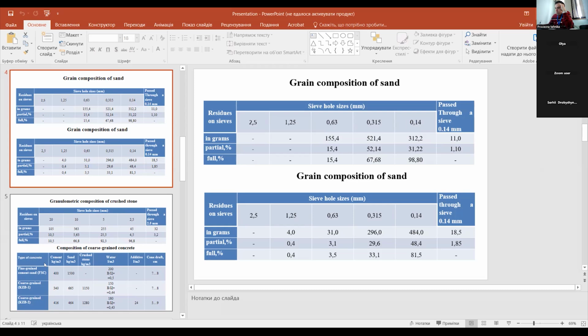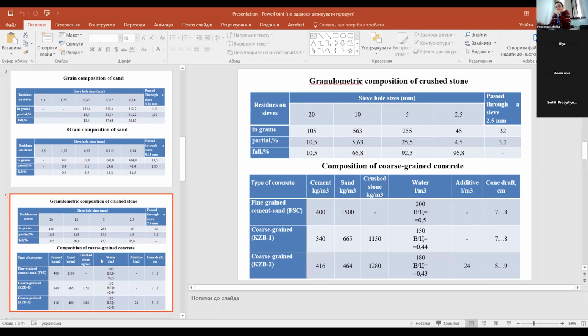The grain compositions of the sand for the fine-grained and coarse-grained concrete samples of the first type are presented in the table. For coarse-grained concrete samples of the second type, the fine aggregate was also quartz sand with characteristics determined in accordance with local standards. The fineness modulus of the sand was 1.18 and its grain composition is shown in table 2. Concrete mixtures were prepared under laboratory conditions.